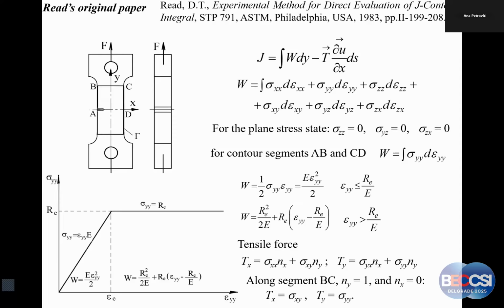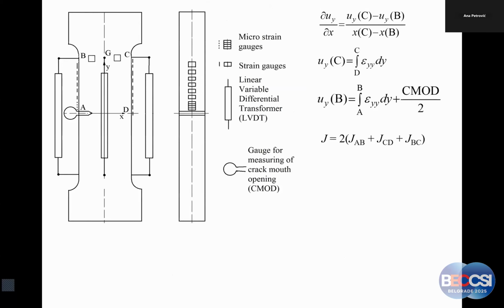So, not going into details, that's not the purpose of this presentation, but just briefly, you can see that we can now calculate strain energy, tensile forces along different segments, and then we also should somehow estimate this component, which is not as simple as the other ones. But that can be done if we also measure crack mouth opening displacement. If we can do that, we can separate components along paths, and we can finally calculate and/or measure J integral.